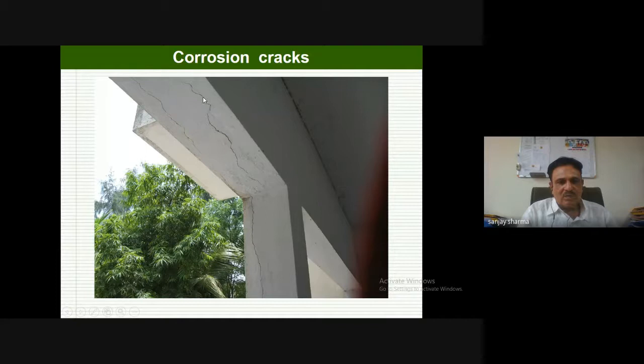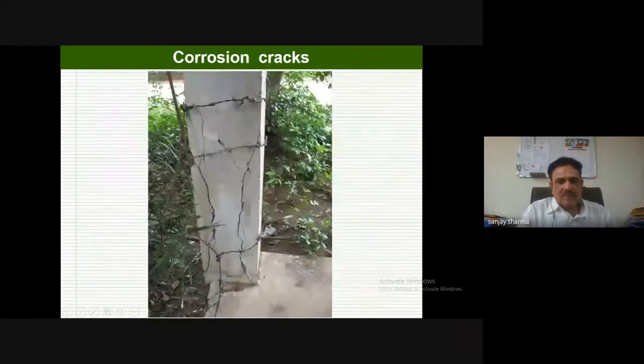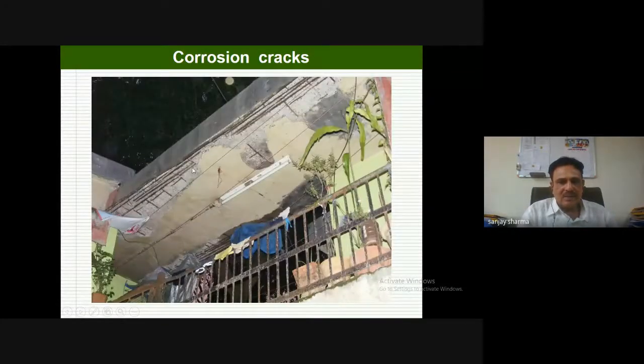Again, corrosion is one of the bigger phenomena, and corrosion occurs due to two reasons. One reason I have already explained is carbonation, and the other is chloride. The difference is that with carbonation corrosion, the crack will appear along the bar and grow parallel to that particular bar. Here you can see corrosion has occurred and spalling has taken place. The crack is going along the bar. This particular spalling has taken place along particular bars.